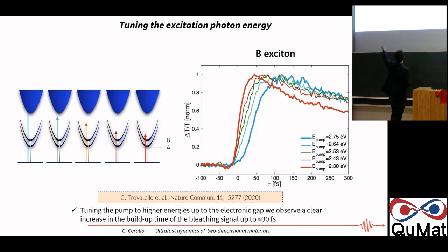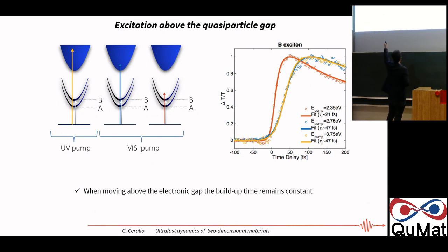Now, we can progressively increase the energy of the pump pulse. So we can give progressively more excess energy to our pump. And we still look at the buildup of the exciton, and we see that now it clearly becomes slower. There is clearly now a rise time, which reaches about 30 femtoseconds for 2.75 eV. So now we can go even higher. We can really go to the ultraviolet. We can pump at 3.75 eV, and we see that the rise time, above a certain threshold, remains more or less constant, on the order of 30 femtoseconds.